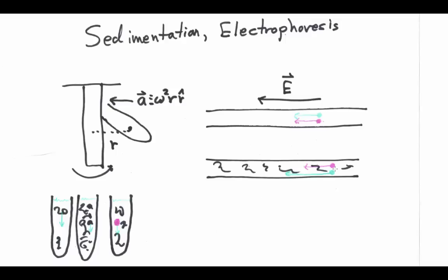Namely, instead of saying we are using this to study separation and how to get better separations, we can say we have a DNA ladder, or RNA ladder. We have a string of single or double-stranded polynucleotides of different length. The molecular weights of these things are known with incredible accuracy, and so we produce a species, and they are all the same and differ from each other markedly. And so we can fire this whole bunch of probes down the solution, the red and green dots, and we can observe how the stuff in the solution of the neutral polymer slows down the red and green dots.